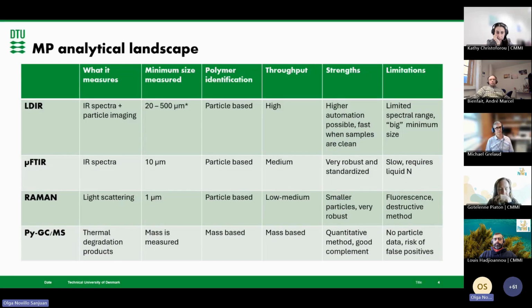which would be 10 micron. Raman spectrometry goes down to 1 micron, and pyrolysis GCMS is a mass-based method, so it doesn't measure particles. It just provides information about the polymeric composition, but not in particles, but in mass, which is also very useful and can be complementary. And also, as always, it depends on what you have available in the lab.